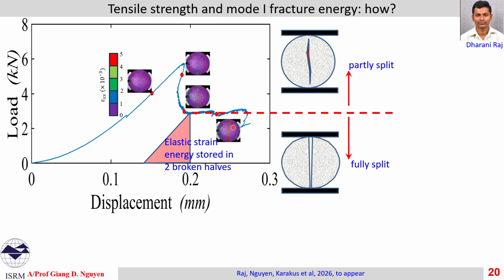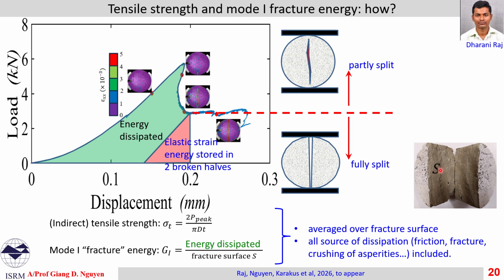Once we have identified that, assuming this is the moment at which the specimen splits into two halves, the two halves can still store some amount of strain energy, assuming this is the unloading slope at this moment. The energy dissipated due to fracture is the blue one here. This is the area limited by this curve. And the fracture surface, in this case, is just the middle of the specimen, which can be worked out.